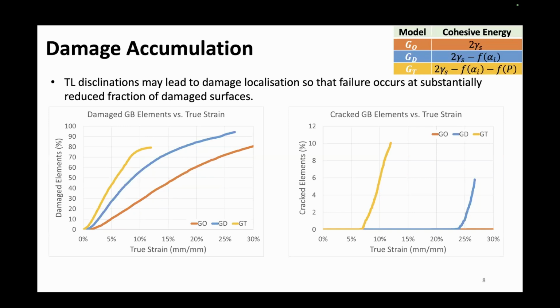And we can see that the GT has the quickest failure rate compared to the other two models, which reaches 80% of damaged elements at around 12% strain. The other two are slower, and the GO, which doesn't include any disorientation or triple junction, is the slowest.